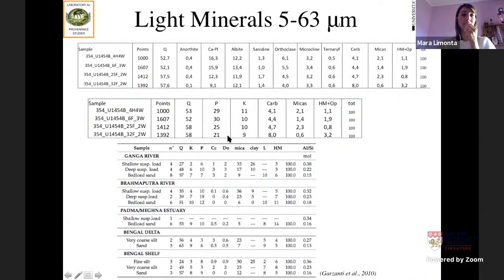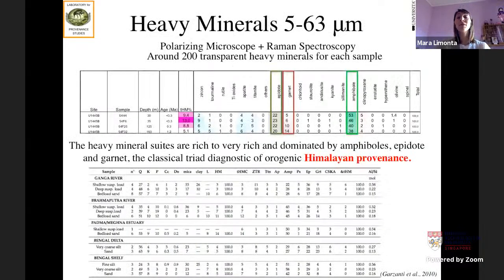What we want to do after, when we also have the composition of the fraction that is bigger than 63, is to compare our data with the two sources, the shelf and the delta, and also the Meghna estuary. If you look at the heavy minerals of this fraction, we analyze them with polarizing microscope and Raman spectroscopy. We analyze around 200 transparent heavy minerals for each sample. And if you look in the core, we have a very rich heavy mineral suite characterized by amphibole, epidote, and garnet that is diagnostic of orogenic Himalayan provenance. We want to do the same, comparing these heavy minerals with the Ganga, Brahmaputra, Meghna estuary, and Bengal shelf.